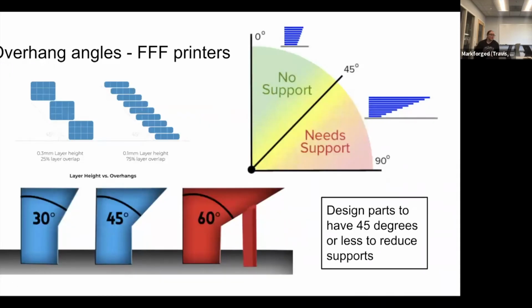So this is something, if you're familiar with 3D printing, that you've probably seen a lot of, is that typically overhangs at 45 degrees are able to be self-supported. However, something that's a little bit more advanced that I wanted to touch on here is layer height. So in the upper left-hand corner there, this is showing that at different layer heights you can achieve different, like better, steeper overhangs depending on your layer height. So the taller your layer height, the less your overhang is supported underneath, and the more you're going to have some drooping, and you might not even be able to get to 45. You might only be 40 degrees from the vertical.